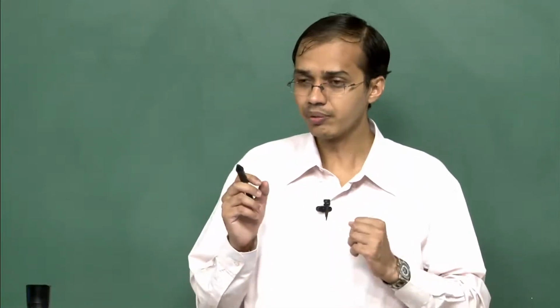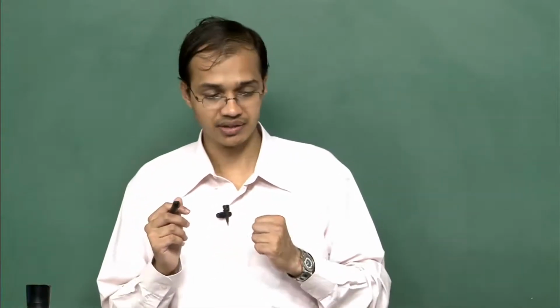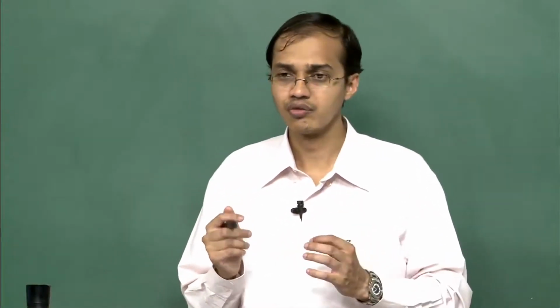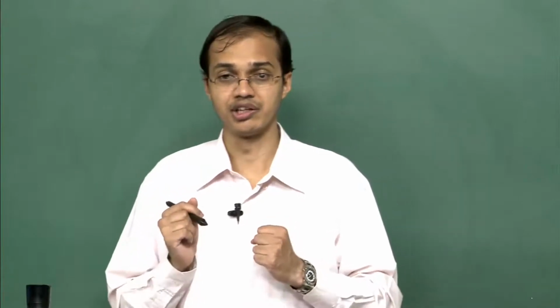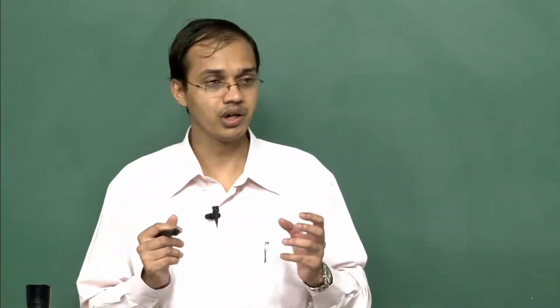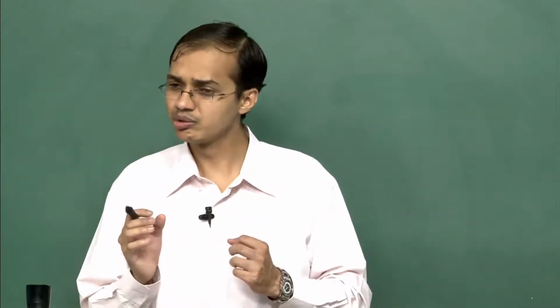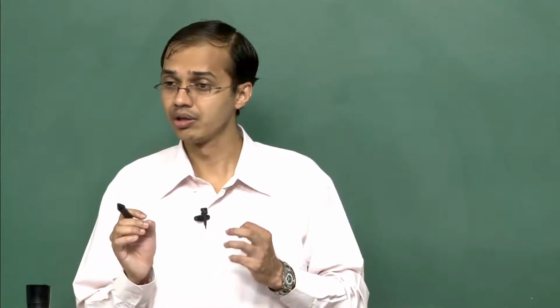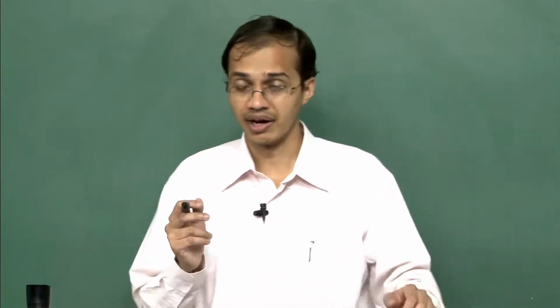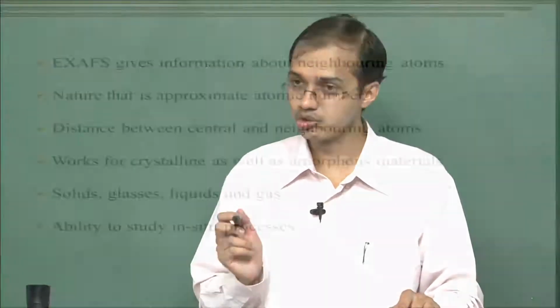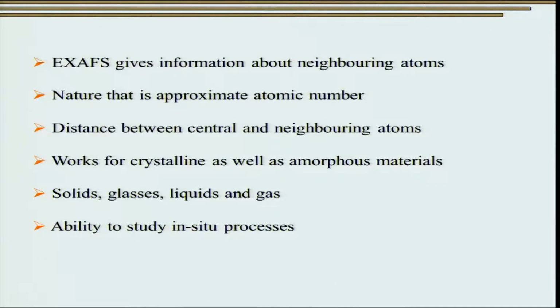Having said that, one of the biggest advantages that we have with EXAFS is that it works very well for crystalline as well as amorphous materials, while X-rays, particularly when we talk about diffraction, give us very little information about amorphous material. At the same time, EXAFS can also be used for studying solids, gases and liquids. Having said that, one of the biggest advantages of EXAFS is in studying in situ processes that occur in different